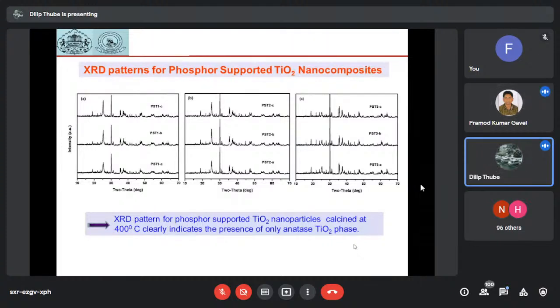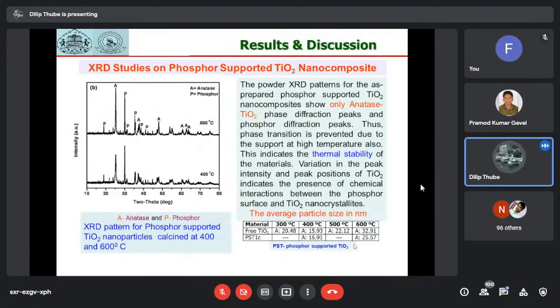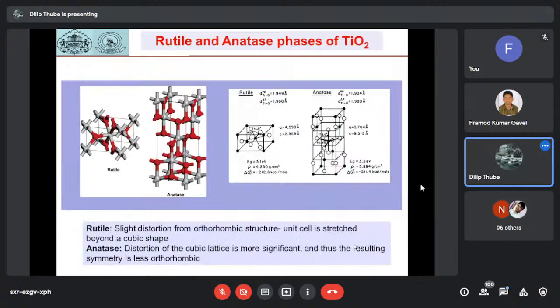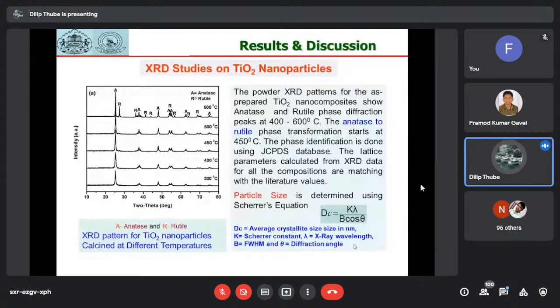Okay. So it is stable at 600 degrees centigrade? Yeah, because see here, what I have shown you, we have gone up to 600 degrees Celsius, and still there is no evidence of a rutile phase. There is only anatase phase. Whereas if you go for pristine TiO2 materials, which are synthesized using the same method, we can call it a control method.